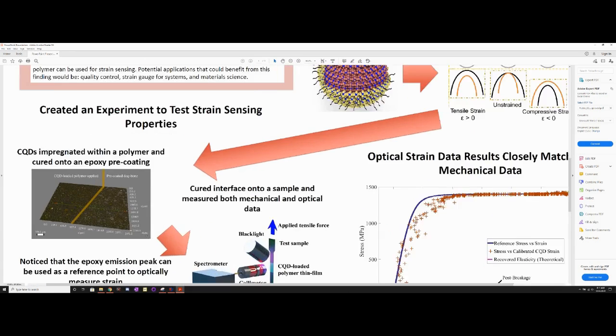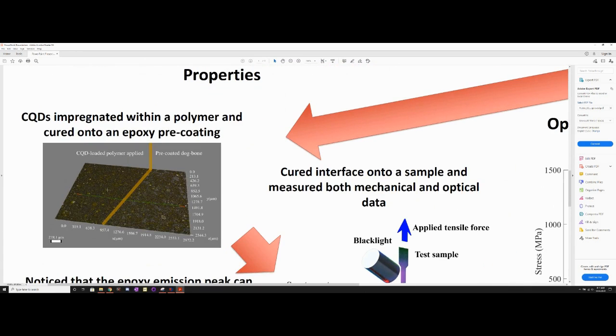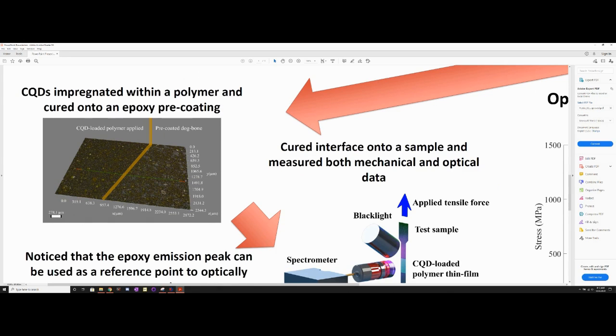And we can apply this within a polymer as a paint onto a pre-coated structure. And what's important here is this epoxy pre-coating that we've used, which is made by Solvay. And you can see here on this 3D surface map that we have the CQD loaded, or colloidal quantum dot loaded, polymer that's applied on the left and the pre-coating on the right. And what's cool is the colloidal quantum dot loaded polymer will actually just go right into all the rough surfaces of the pre-coating, which is useful for adhesion in realistic applications such as aeronautics.